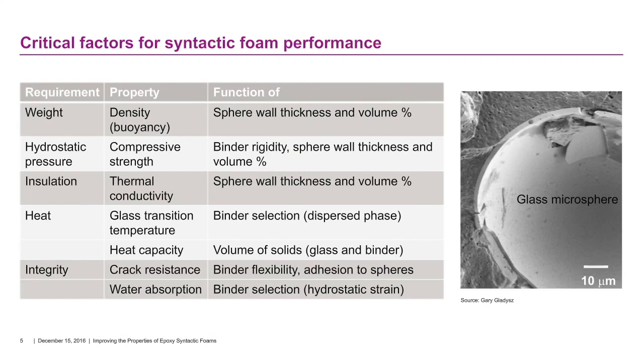Sphere wall thickness and loading level also come into play regarding insulation and the need to have the lowest possible thermal conductivity to truly insulate the pipe and its contents. The ability to withstand heat is a function both of the microspheres as well as the binder. In this case, the matrix, we're talking about epoxy as the dispersed phase. Epoxy glass transition temperature can be absolutely improved via optimal selection of thermal curatives.